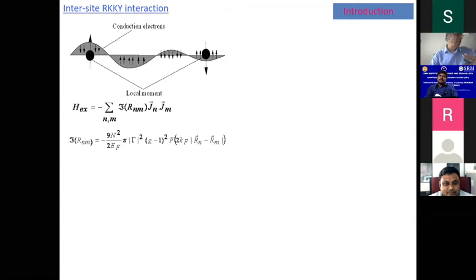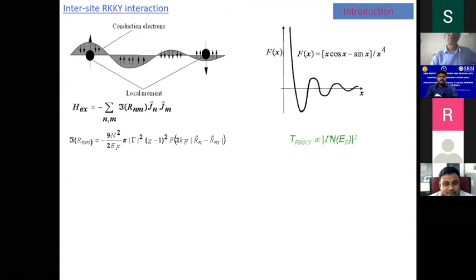Now, let me go to another important topic. I have 15 minutes, I have to finish quickly. When you talk about magnetic ordering, I talk about two important interactions. I mean, there are many interactions, but let me skip those. When you talk about a simple rare earth or simple metal, the interaction that causes magnetic ordering is called indirect exchange interaction. That's called RKKY. Through these oscillations, a 4f local moment here can polarize the conduction band. The strength is strong here, and as you go away from the rare earth, it gets weaker and weaker.